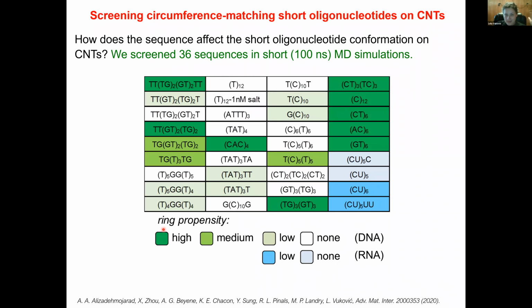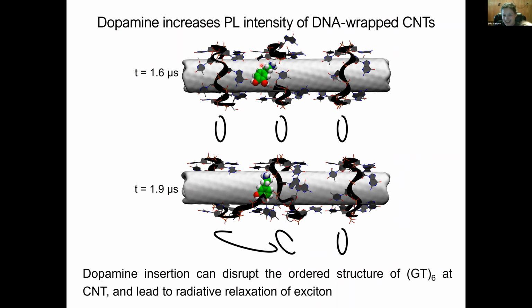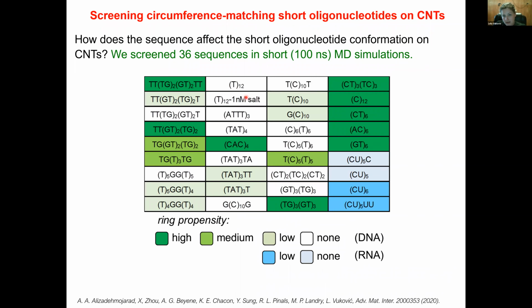So seeing these rings was quite unusual for us. So we did a follow-up study, also with the help of TAC, because we did a lot of screening. We did a follow-up study to check whether other sequences also form rings if they have the correct length. And so we screened a lot of the sequences and found that ring formation on carbon nanotubes is definitely sequence dependent. Some sequences, you can see if they're in green, have a high propensity to form rings. If they're in white, or light green, some of them, they don't form rings. So through screening, we observed that.